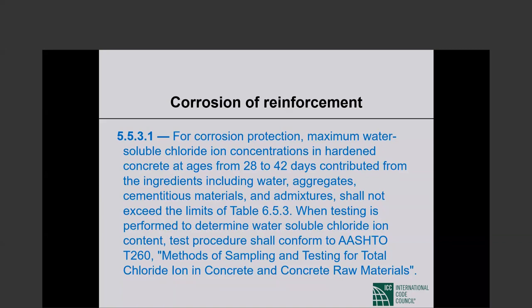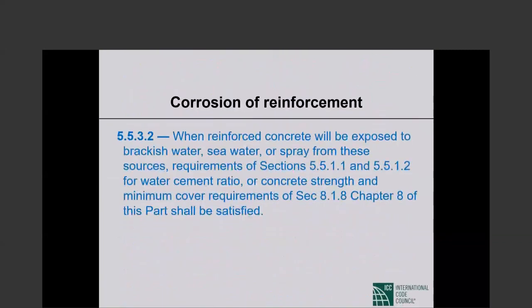This is extremely, extremely important for Bangladesh. There is a corrosion problem in most of the country, particularly in coastal areas. Chlorides cause the corrosion. The chlorides from all sources have to be limited, severely limited. When testing is performed to determine water-soluble chloride ion content, the test procedure shall conform to AASHTO T260 that I had in mind when I was talking a minute ago.